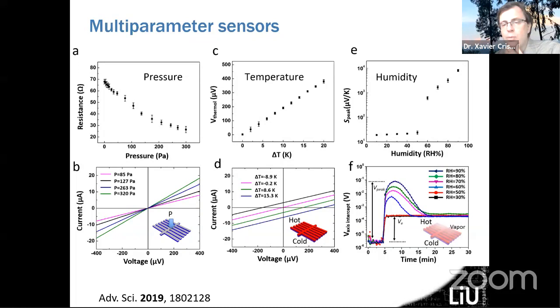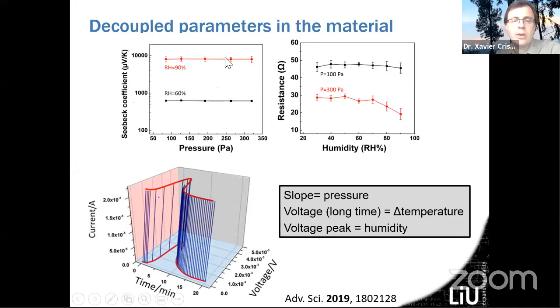As I told you before, when you plot this versus time, the peak value gives you the humidity, but the plateau value after a while is related to the electronic Seebeck voltage. So if you know the electronic Seebeck voltage, you can know the temperature gradient. This is what we succeeded to do, basically. And the amazing thing is that those parameters are not cross-talking, they are not polluting each other.